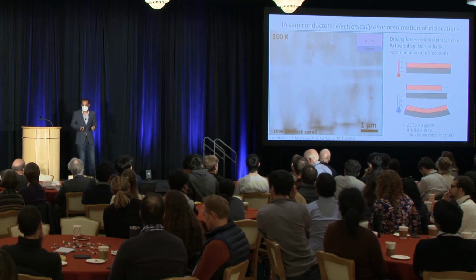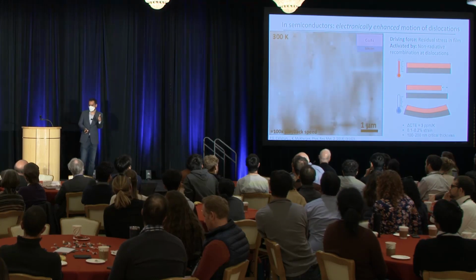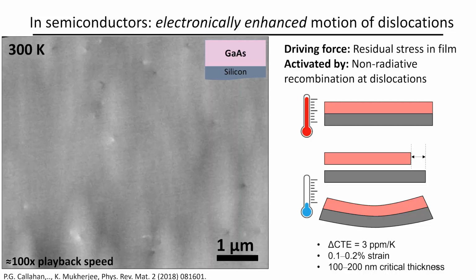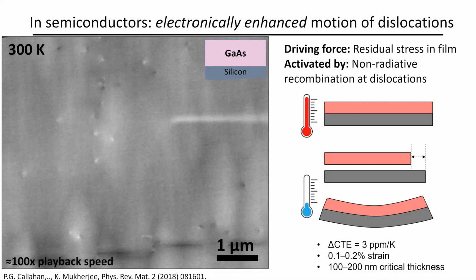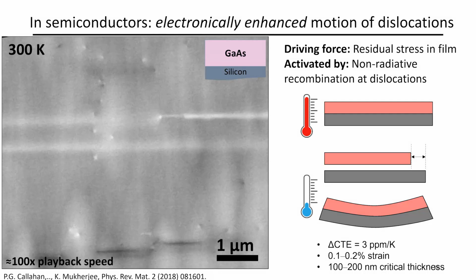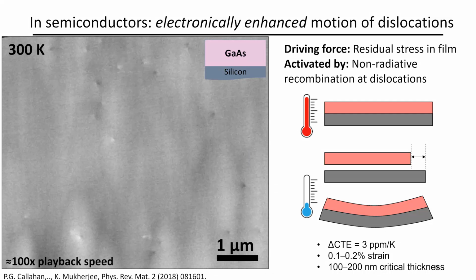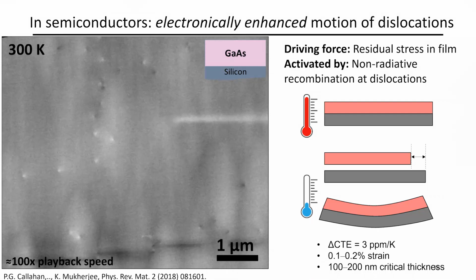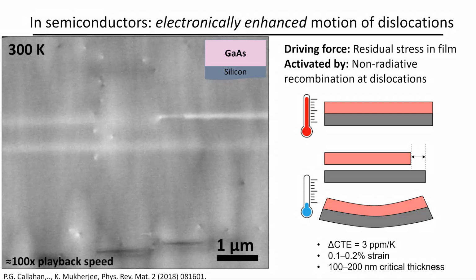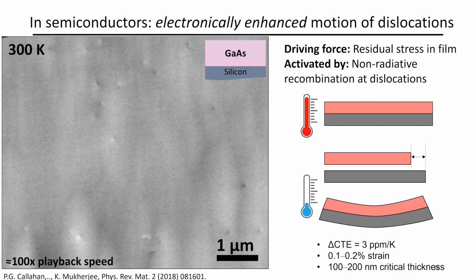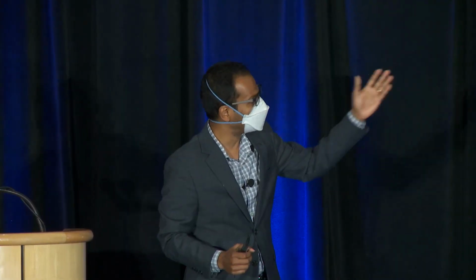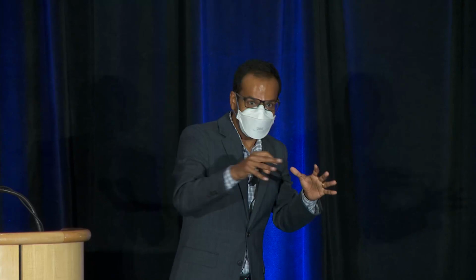The reason why a lot of the dislocations move when you grow these materials on silicon is because in addition to the lattice mismatch, there's another bigger mismatch that people don't talk a lot about, which is thermal expansion mismatch. So most people grow semiconductors at high temperature, and they cool it down to take it out of the oven, yeah? And at that time, the thermal expansion stress really builds up in a lot of these films. So most of the semiconductor films, these light-emitting semiconductors, have huge thermal expansion strains. So not only is the material soft when you inject electrons into it, but there's huge stresses, so the dislocations want to zip around as fast as possible in your material.